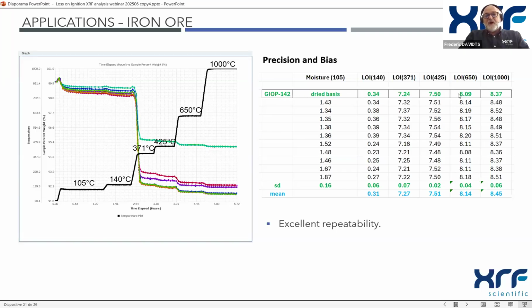Again, we are working with reference material, the GIOP-142. Here we have the result of the certificate, and we have multiplied the analysis for a couple of crucibles, and we can see that we obtain an excellent repeatability, so very good precision, and the bias is very close. So we have something really close to the reference, and this for all the temperatures. That's of course really good, and also I prefer to say that we have a couple of standards available with a certificate value for the LOI, and it's not so easy to find standards with the LOI value.